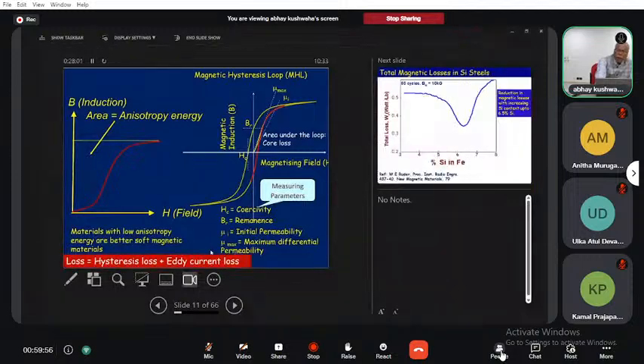And if we go for a complete cycle, we will get a hysteresis loop, and the total energy of this hysteresis, or total area under the curve, is called the core loss, or area under the loop is called the core loss. So our attempt should be to keep this core loss as low as possible, and also how we reduce the eddy current losses. So as we told, the losses are the hysteresis loss and the eddy current loss.